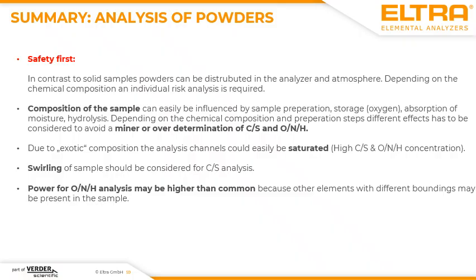Swirling of the sample is especially one problem for CS analysis, because the more finely divided your powder is, the more the combustion of the sample in the crucible can affect the correctness of your results. You can solve this problem by application of lids, which maybe affects the sulfur measurement, or you can apply a special combustion procedure which allows you to process these samples safely.